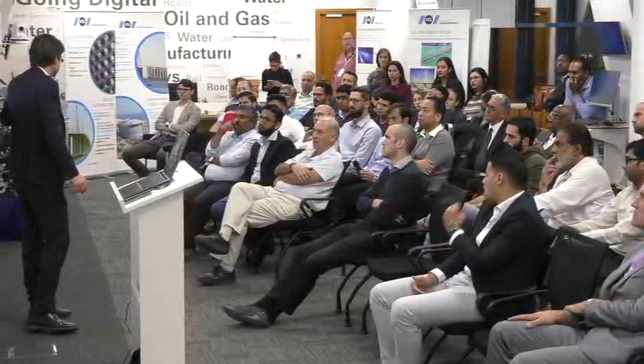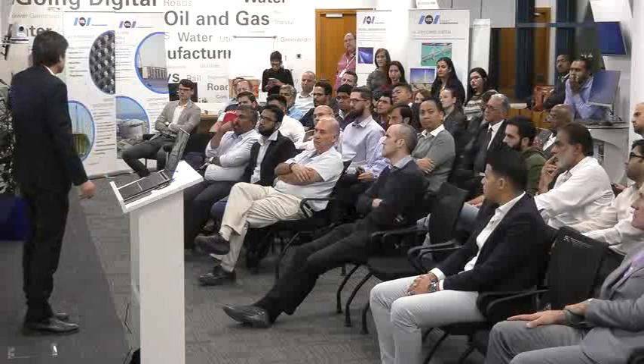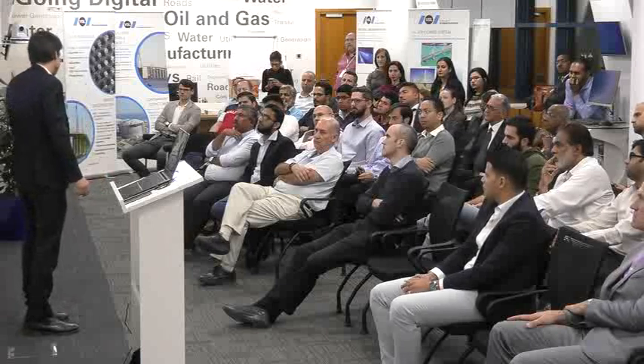Today, we are relying on this strand. Why? Because it has a very low relaxation. And now we choose technology which is multiplying by more than two the relaxation. And on top of this, we have a test, and this strand has low redundancy, meaning that you do not lose one wire, you lose a complete section. Yeah. It's a localized corrosion. Exactly.